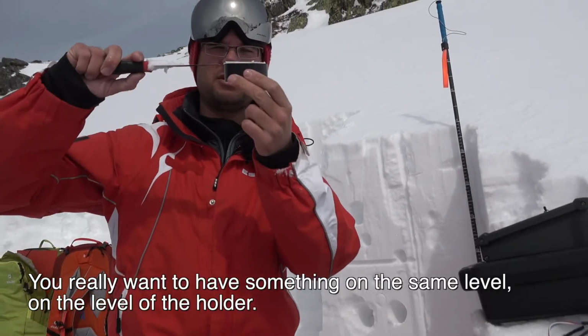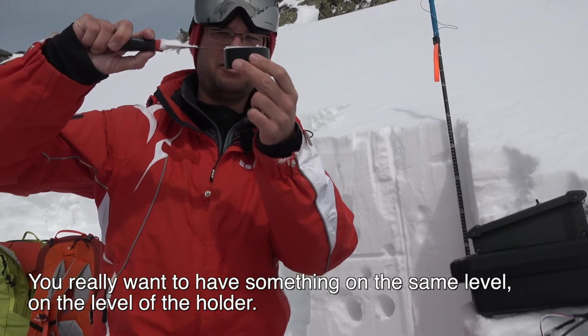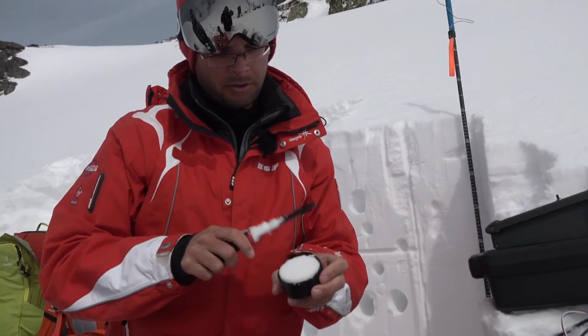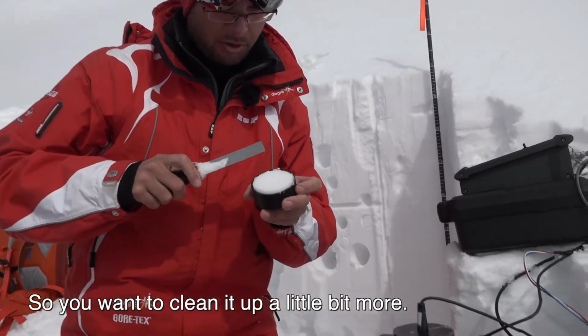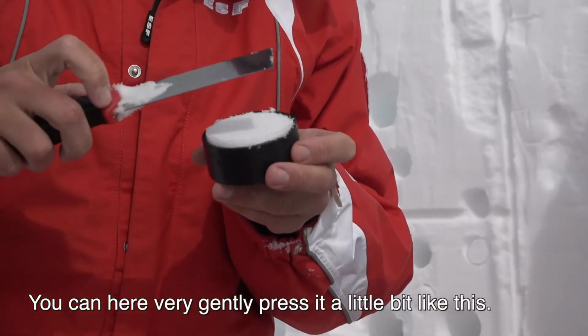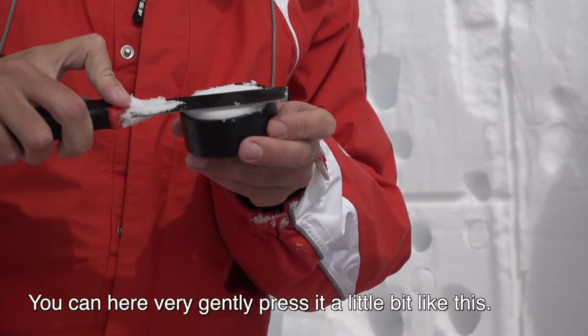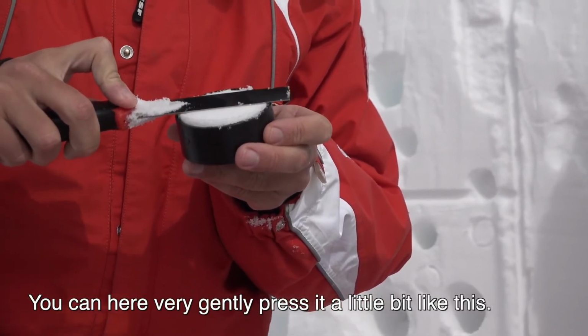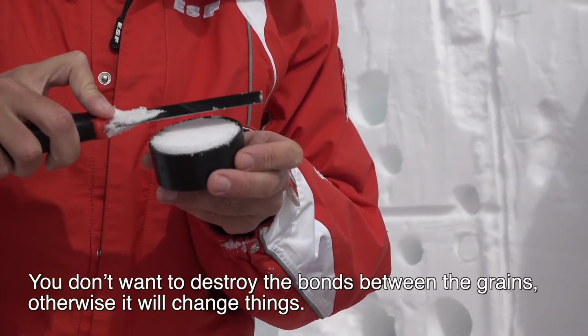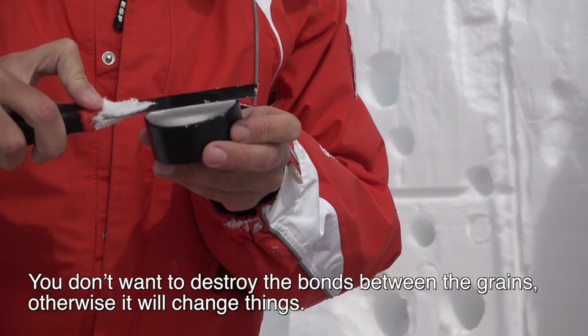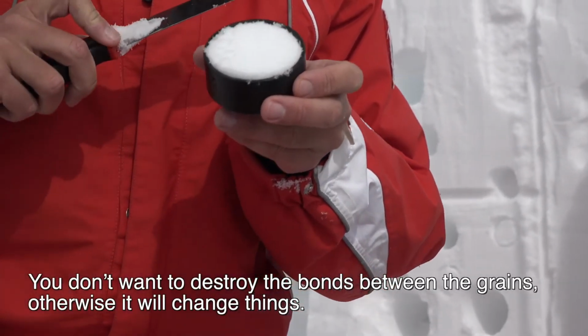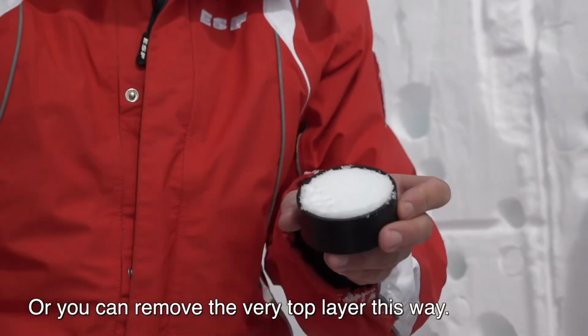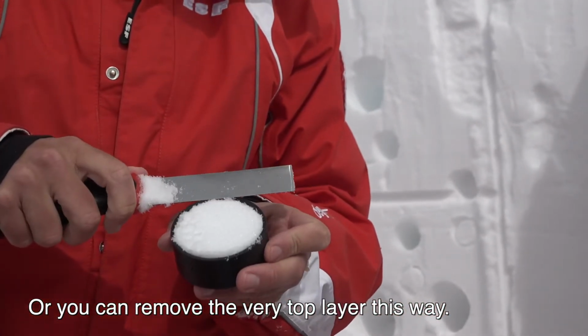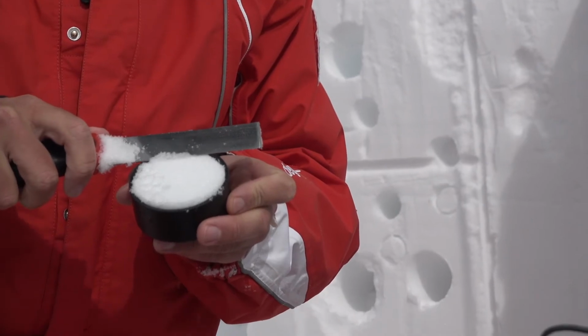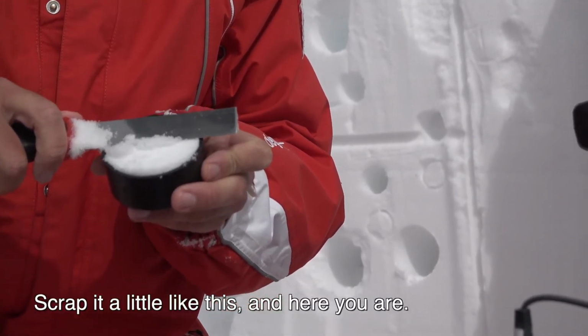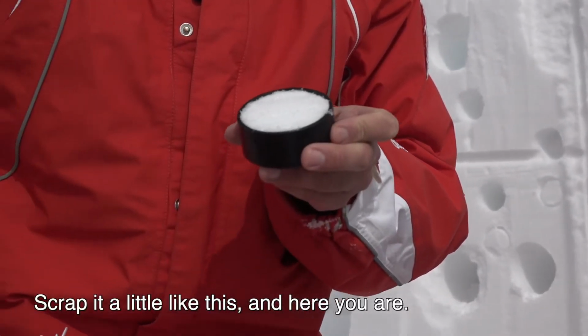The idea is that you really want to have something at the same level as the holder, so you want to clean it up a little bit more. You can very gently press it a little bit like this. Basically, you don't want to destroy the bonds between grains, otherwise you will change things a little bit. Or you can this way remove the very top layer. You just scrub it a little bit like this, and here you are, right?